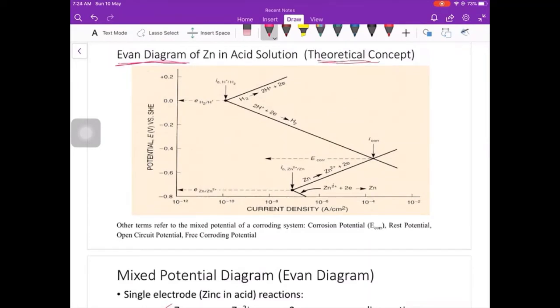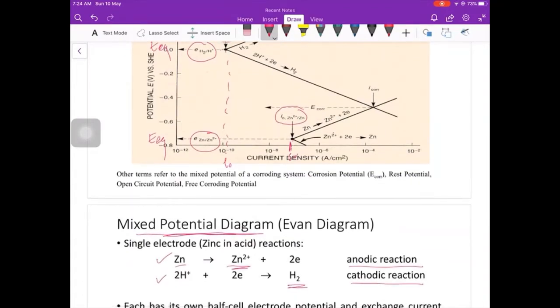Okay, so you can plot the Evans diagram theoretically. We also call this the mixed potential diagram. Okay, so look at this diagram. You can find E equilibrium here for metal zinc, and also E equilibrium for the cathodic reaction, hydrogen evolution. On the diagram, you can also find the i0, the exchange current density, for the metal, and this is i0 for the cathodic reaction, hydrogen evolution.